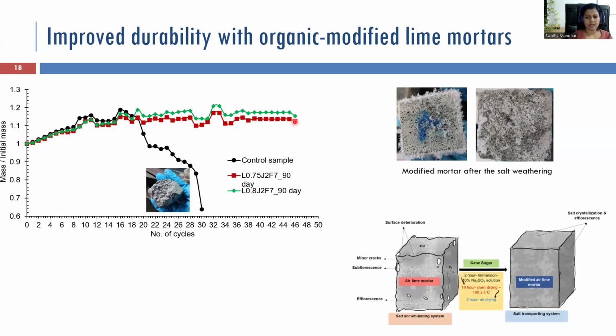This is our illustration from the understanding that we developed. The first one, with pure lime mortar, could act as a salt accumulating system with smaller pores. Salt could go and accumulate and cause damage because of crystallization pressure.